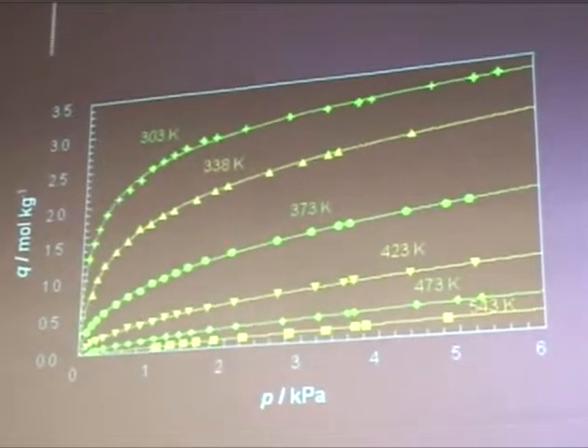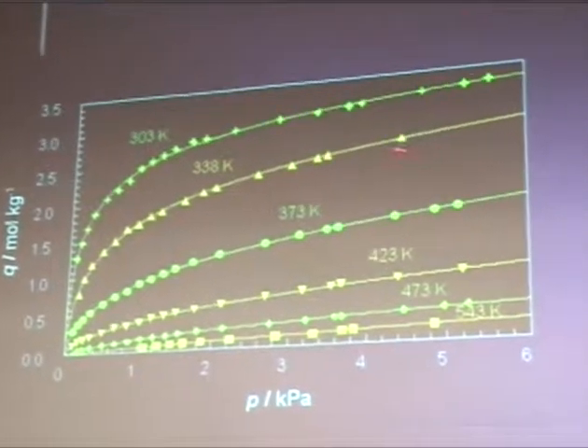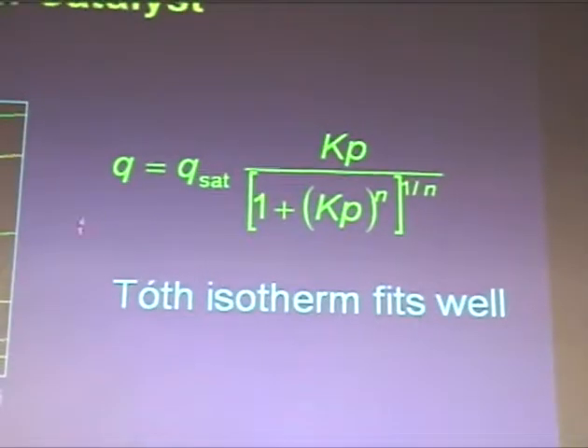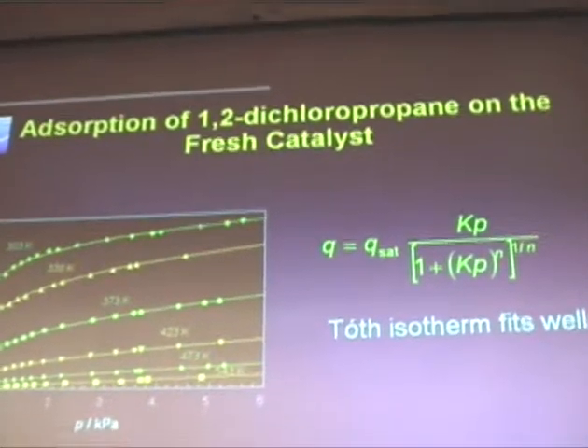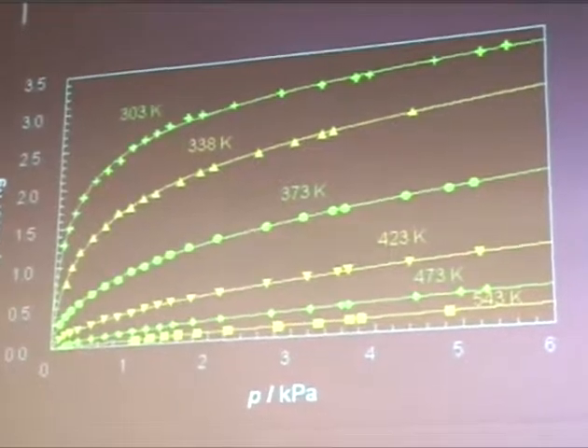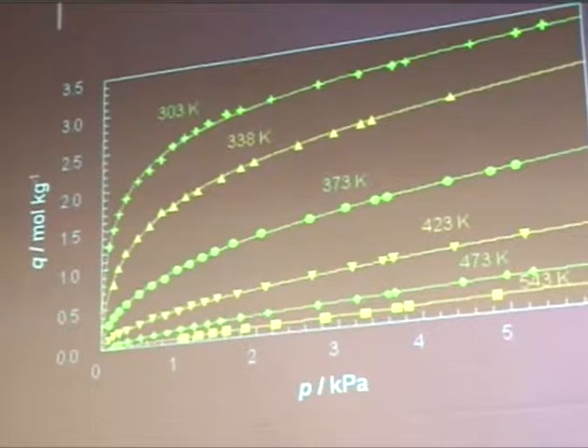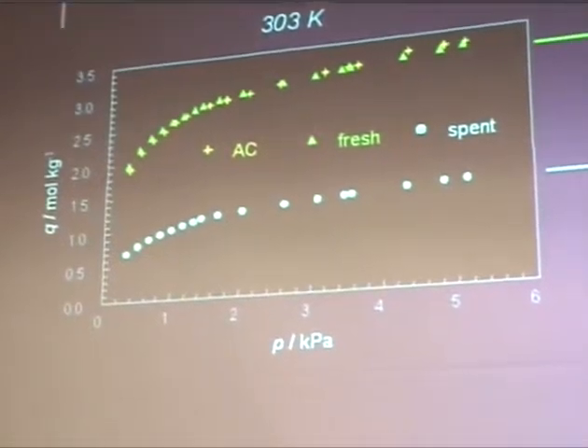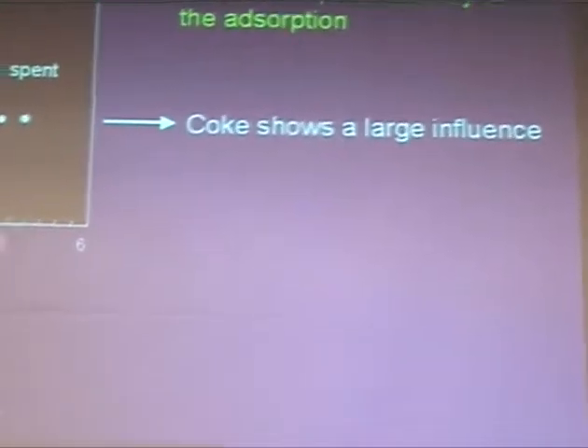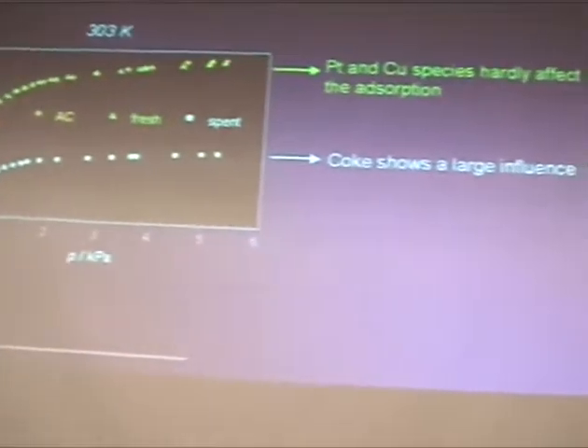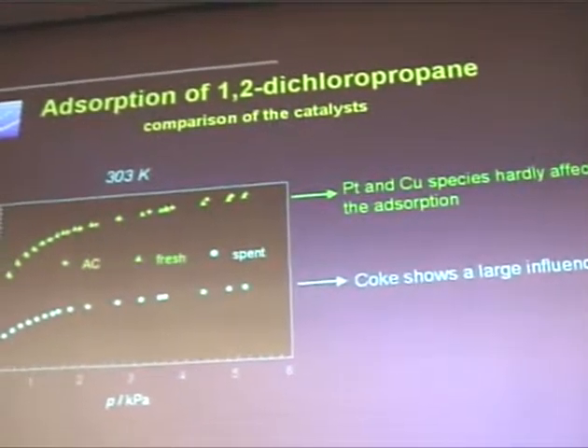When we look at adsorption of the reactant, not under reaction conditions, you see that the Tóth isotherm fits well, as it usually does for activated carbon measurements. It's a good model. It's semi-empirical, and you can come up with an interpretation. Then when we compare the three systems at room temperature, we see here the active carbon and the platinum-copper. They're the same. The spent catalyst shows a much lower adsorption, and no one will be surprised at that. The other way around, you would not believe me and would probably go for coffee.